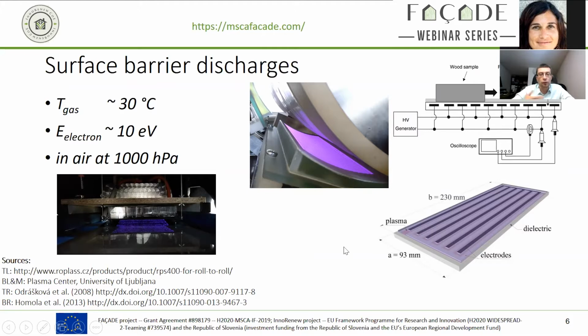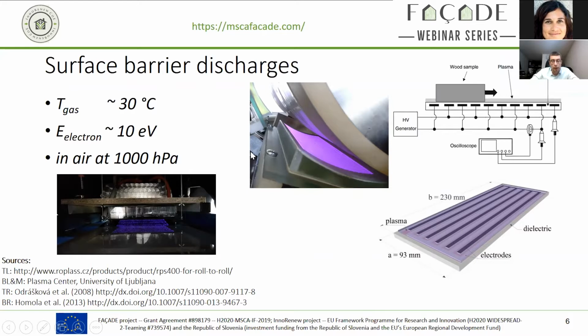The point that's important to observe with these kinds of discharges is that the plasma is not igniting in a large volume, but only really on top of the surface. So we need to come in relatively narrow for our substrates. This works really well, very energy efficient at very low temperatures. It scales in 2 dimensions, so the scaling for large surfaces is very simple. This is independent of sample thickness. However thick your workpiece is that you want to treat, this will work, but only on relatively flat or evenly shaped surfaces. If there's a whole 3-dimensional structure, then it's difficult to properly apply this kind of setup.